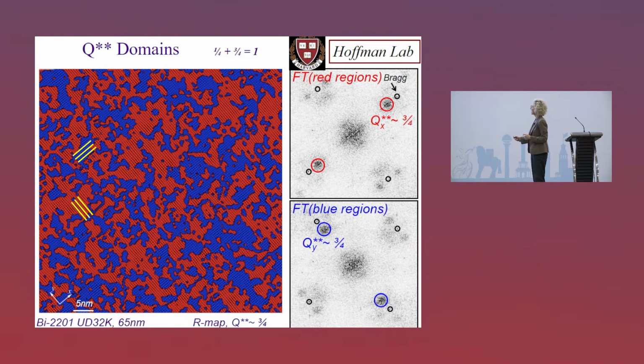And then there are these satellite peaks that can come up that indicate local charge density order. And they're in two different orientations. So here, if they're along this diagonal, then we color them red. If they're along this diagonal, we color them blue. So for example, in this region, where the stripes are running diagonally to the right, the wave vector appears here. And so we color those regions blue. If the stripes are in the other orientation, diagonally to the left, we color the regions red. So this is a map coloring the orientation of the stripes in this system.